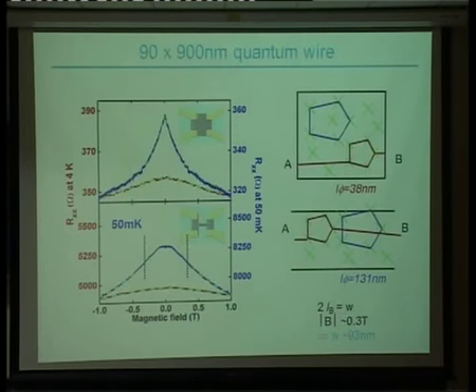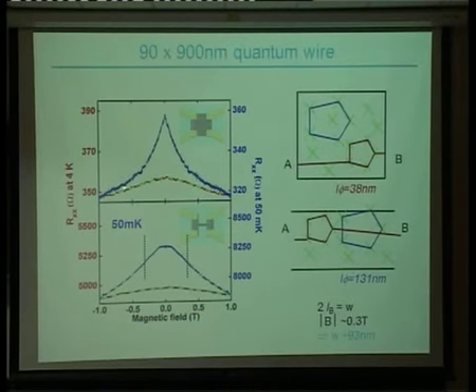So this was really the first time that anyone had measured something where they'd actually seen lithographically where the dopants were placed, and they could independently confirm it using electrical measurements. What's the temperature of the high temperature one? So 4 Kelvin and millikelvin, 50 millikelvin.